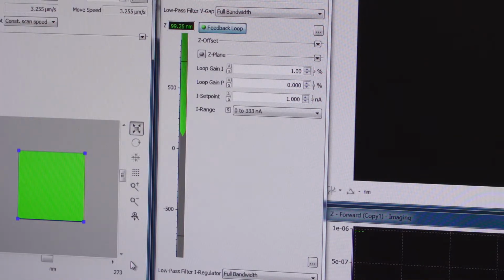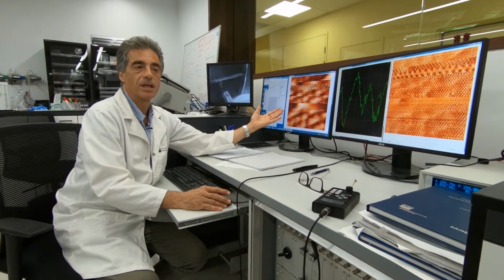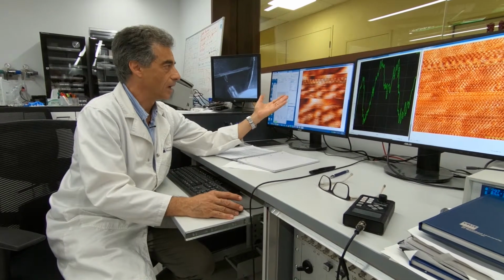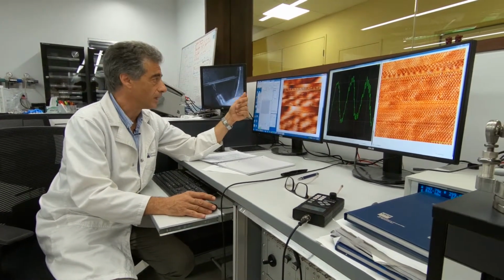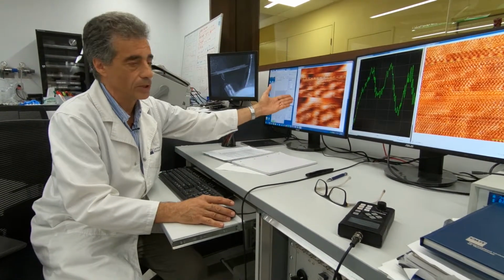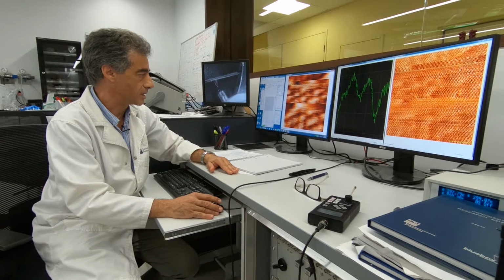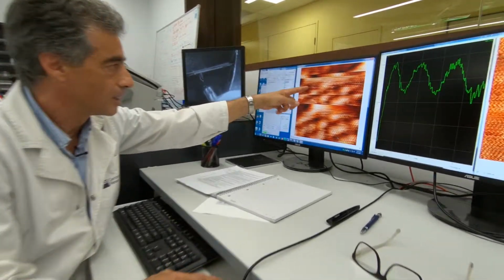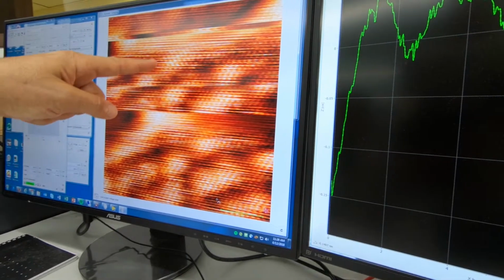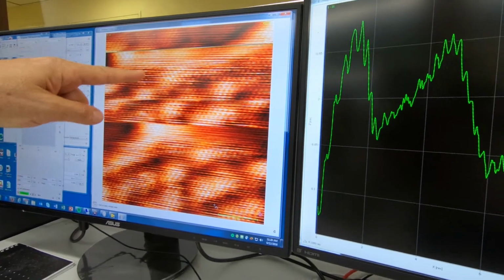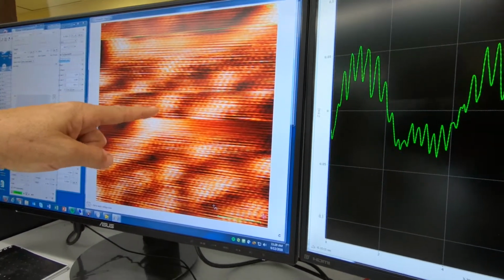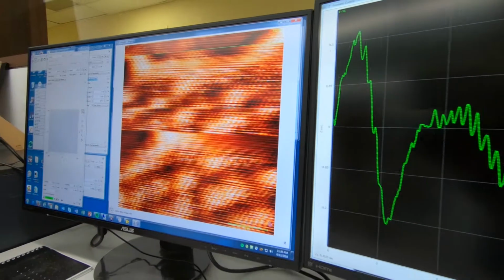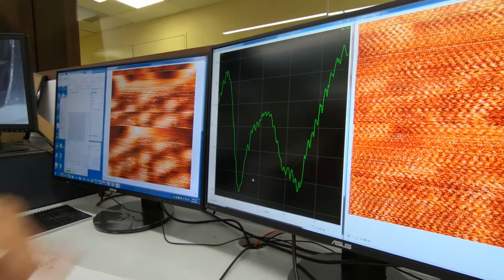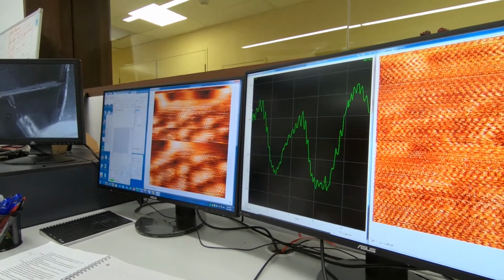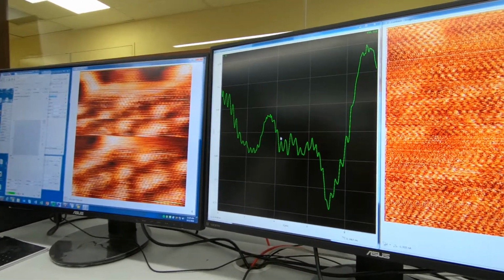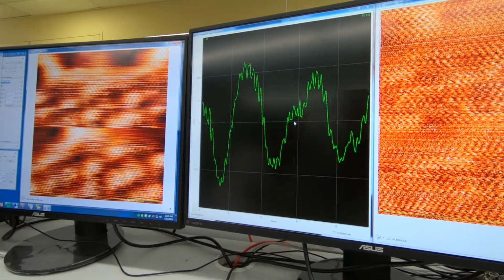Let's start the scanning. When we scan, what is here on the screen is a representation of the tip movements in Z and in X and Y. And these movements are actually following the atomic structure of this surface. And here we are. We see the graphene. You see there these little spots. These are the graphene atoms that are coming out. And the black dot is actually the representation of a graphene hexagon. You can see on this XY graph the representation of the movement of the tip. And you see these little bumps here. Each one is a graphene atom.